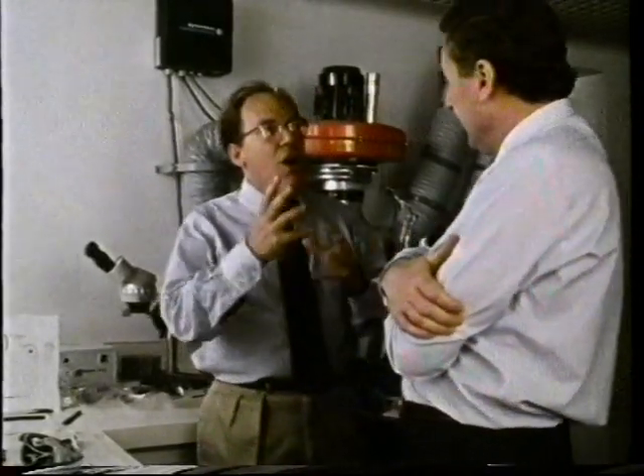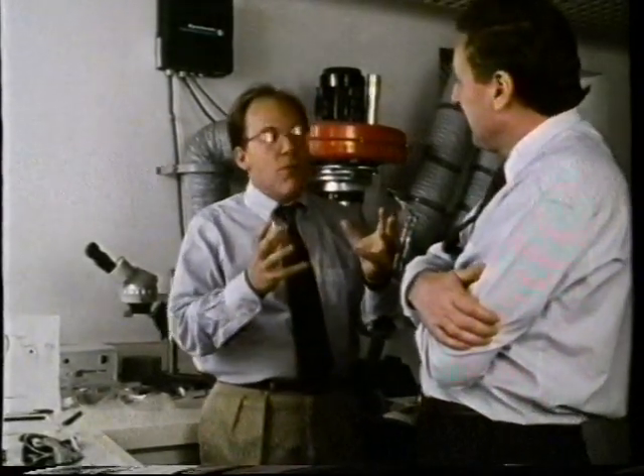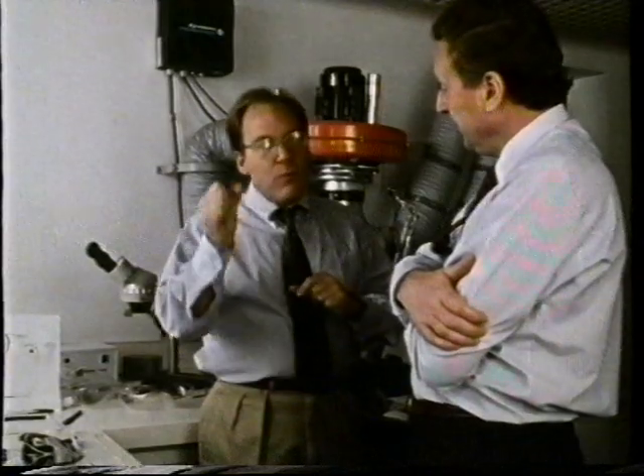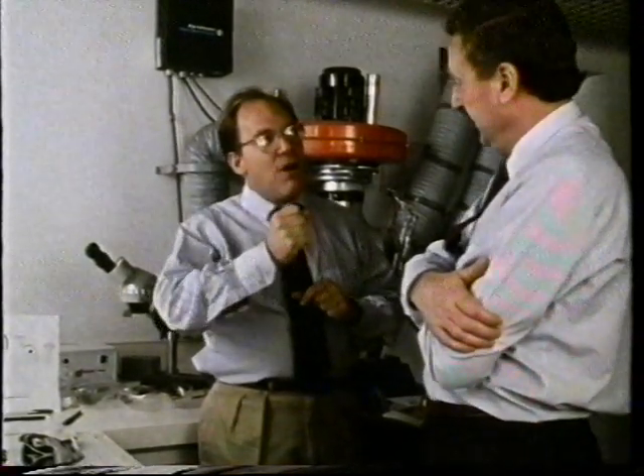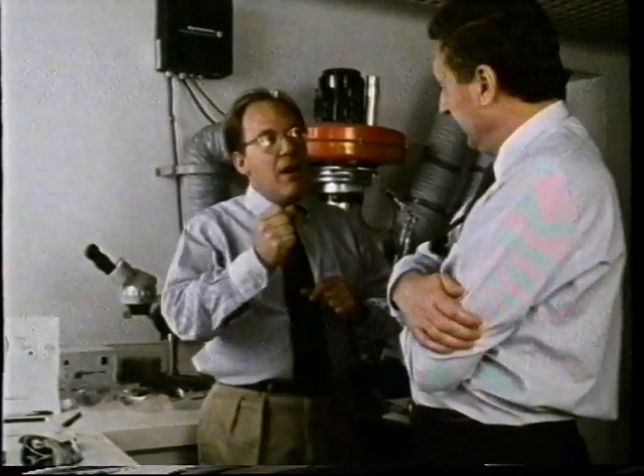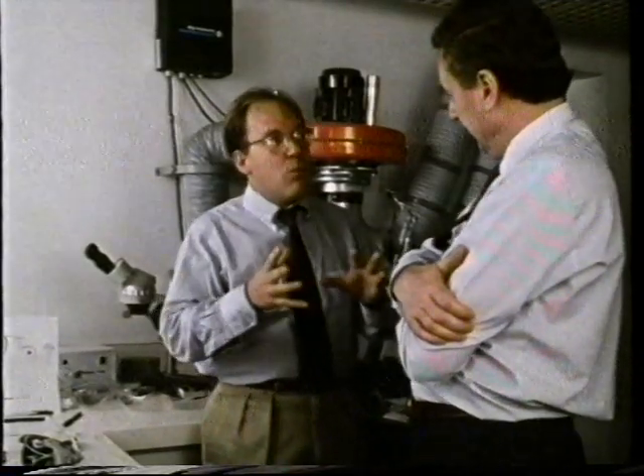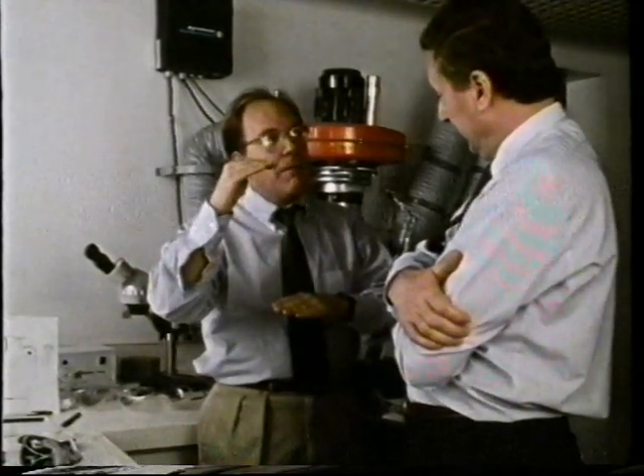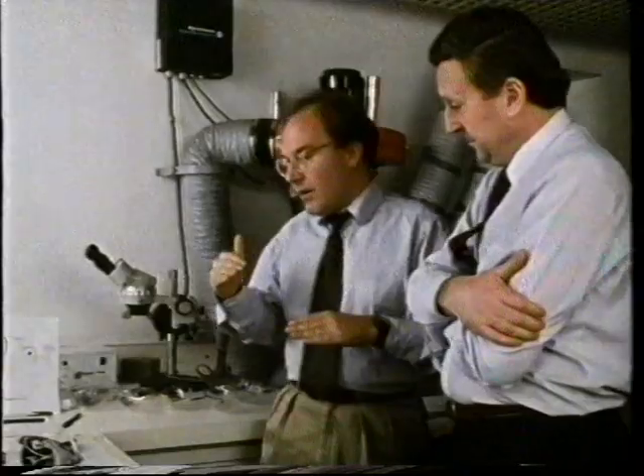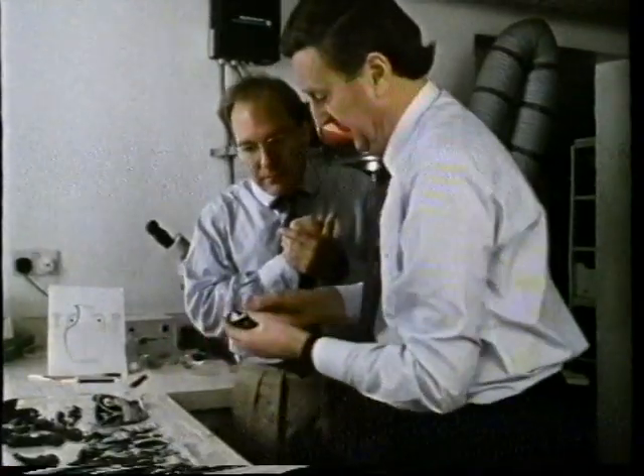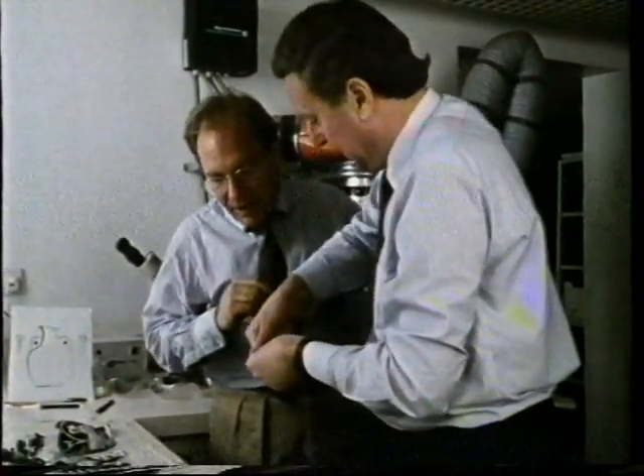It's pretty clear to me that a rather thick, elongated bubble of blue glass was formed. And then it was dipped in a pot of white glass. And if you look at the piece, clearly it wasn't dipped in all the way up to the neck, up to the top, because you see that the lower handle attachment point shows that the handle was put down on white glass. That's right. It's clear, actually, as pressed onto the white glass.